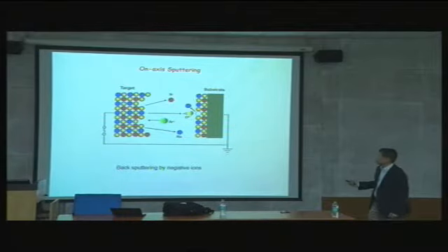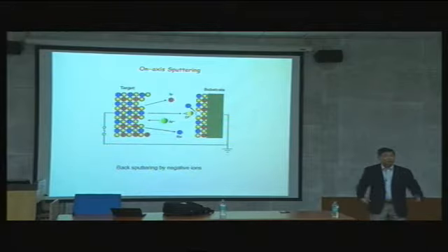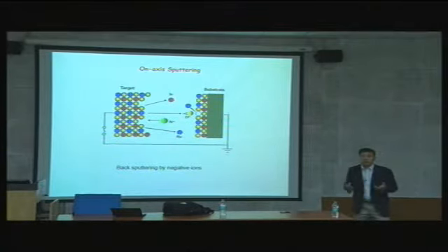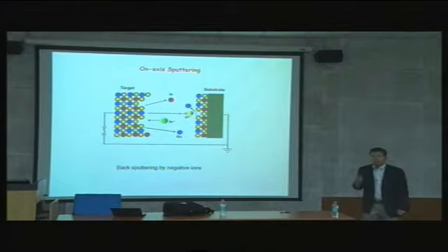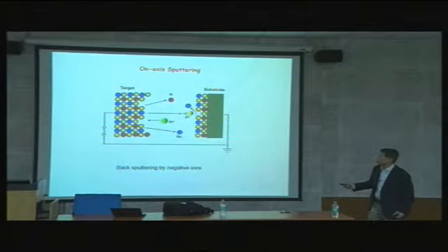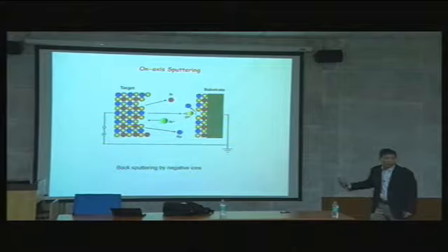But look at this, oxygen also comes out from the target because the ceramic target contains oxygen. So when your oxygen comes out, this oxygen is an oxygen minus 2 ion. And this one is a problem because this one is negatively biased, by a few hundred volts. And a few hundred volts attract this positive ion to hit it, knock out this.